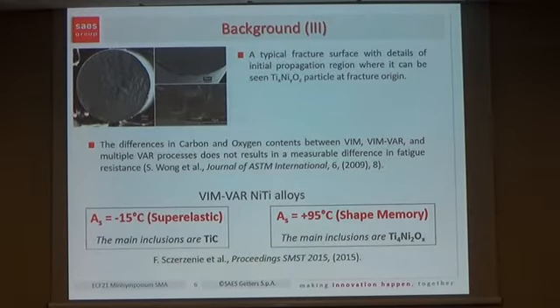Well, typically, as most of you know, looking at the fracture surface of, for example, a nitinol wire is not unusual, but typically there is always an inclusion present at the crack tip. In this case, it is what we call typically intermetallic oxide, Ti4Ni2O, sometimes not stoichiometric, and sometimes titanium carbide, that is the other main inclusion. The differences in carbon and oxygen content.